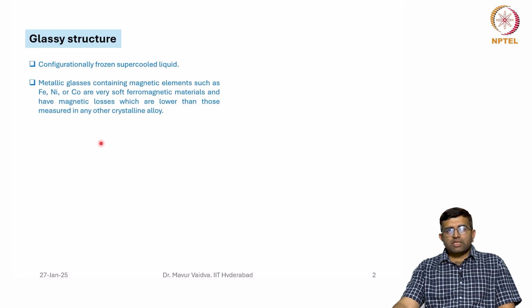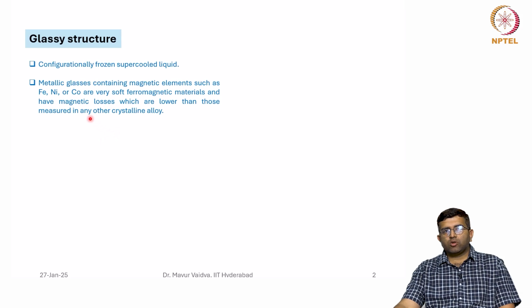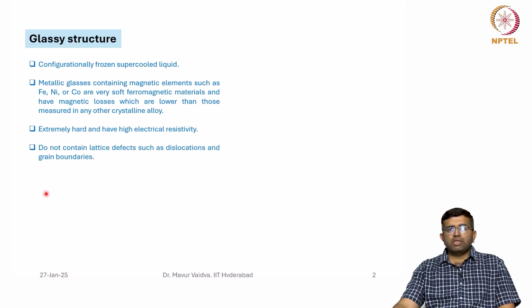So, metallic glasses which contain, for example, magnetic elements such as iron, nickel, cobalt are very soft magnetic materials and have magnetic losses which are lower than those measured in any other crystalline alloys, and that is why they find a lot of application in magnetic devices. They are extremely hard and have high electrical resistivity. These glasses do not contain lattice defects such as dislocations and grain boundaries.